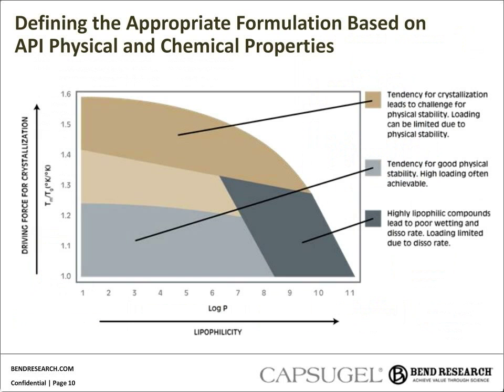And then, as with the previous map, here we are looking at how we think about how to formulate amorphous solid dispersions. In this case, what we're looking at on the y-axis is the driving force for crystallization, or the melting point to glass transition temperature ratio, plotted against the log P, or lipophilicity, of the compound. And we have guidance maps like these to help us, before we start to make any powder at all, look at our historical experience with this technology and the compound properties of what we're receiving, and say, last time we saw a molecule with these types of properties, what types of formulations worked, what were the problems we were trying to solve. And so using maps like this, we can capture that historical experience.